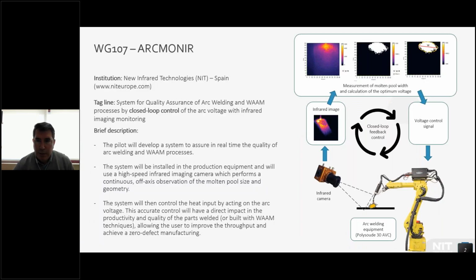Just a brief overview of the pilot. This is similar to the presentation that we showed in the kickoff of the project. The main goal of ARCMONIR is to build a closed loop feedback control system to control the voltage of the arc welding using an infrared camera that is measuring the melt pool width and calculating the optimum voltage. This is what I'm showing in the diagram on the right. So we have the camera that is looking at the process area. Then this image is being analyzed. We obtain a measurement of the melt pool width, and then with that we can calculate the optimum voltage and drive the voltage control in the Polysoude torch. And with this, the aim is to improve the quality of the whole process.